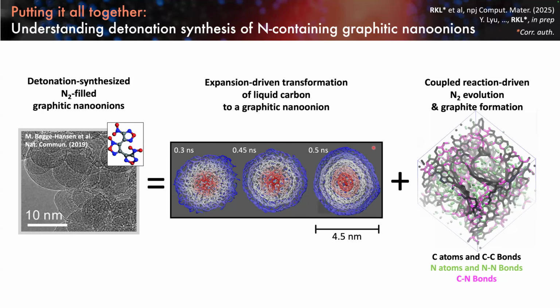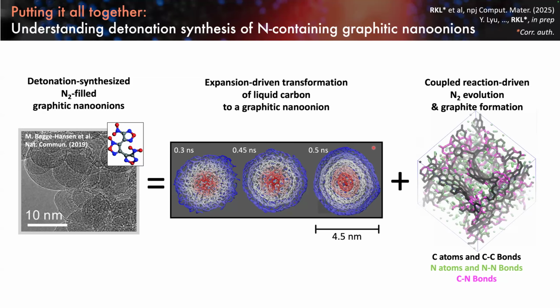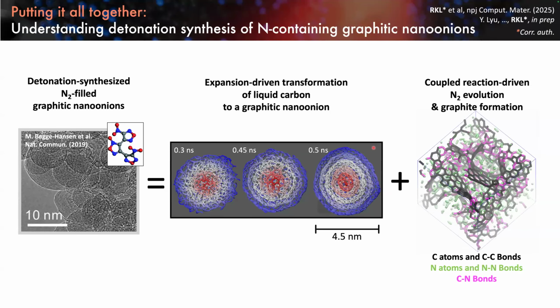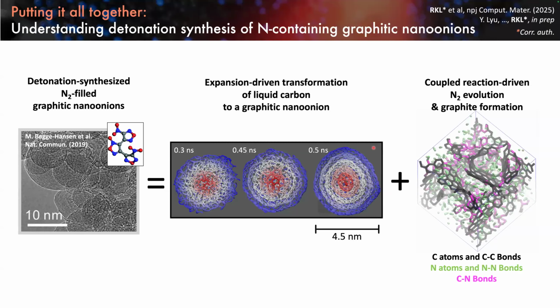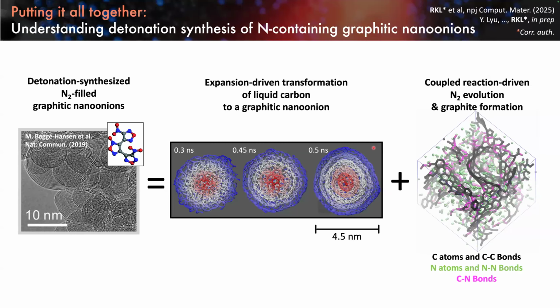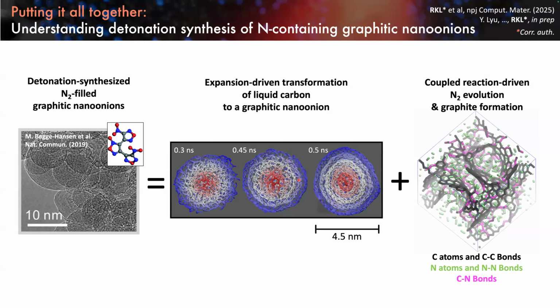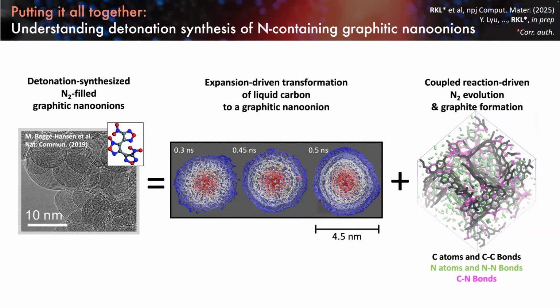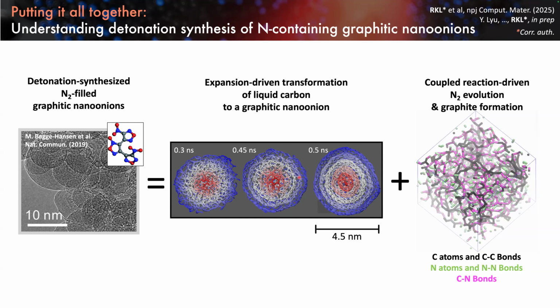As you begin to drop the temperature and pressure as you adiabatically expand, the particle is going to want to solidify. As the solidification is happening, that's when your nitrogen would want to come out. However, that solidification is happening from the outside in, which suggests at least some of that nitrogen has got to get trapped inside of the particle and pushed to the core as you extend that solidification. So our simulations would suggest that the stuff inside the core of these particles is likely nitrogen in the molecular form.